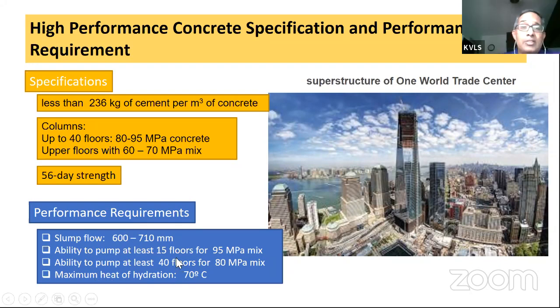The other performance requirement that was put in place was to minimize the heat of hydration. The maximum heat that the concrete could produce is only about 70 degrees Celsius. This becomes very important because the podium, the basement raft of this structure, was almost 3 meters deep, and this very stringent requirement of very low heat produced in the tower was put in place for the concrete mix that was developed. So that means that the contractor basically had to hire a specialist concrete mix designer who could deliver concrete that met these performance requirements going forward.